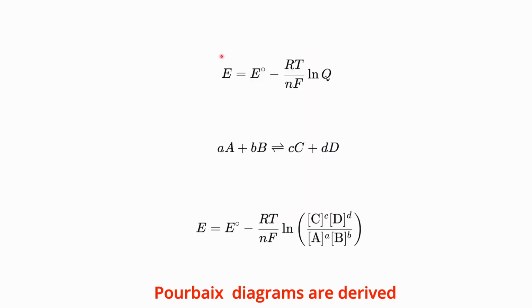Pourbaix diagrams are derived using the Nernst equation. The Nernst equation allows the calculation of the potential for an electrochemical equilibrium under non-standard conditions. It is derived by subtracting a term from the potential under standard conditions, which equals the gas constant R times the temperature T, divided by the product of the equivalent number N and the Faraday constant F, multiplied by the logarithm of the reaction quotient.